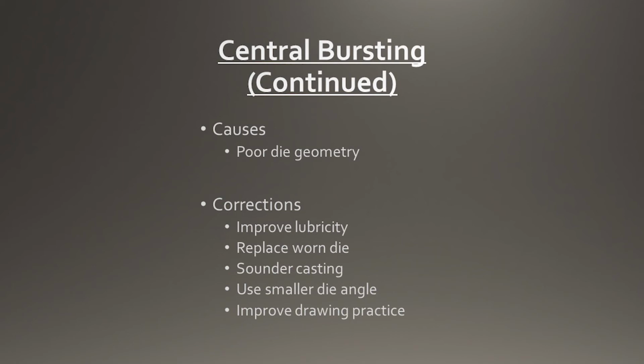Sounder casting, that's interesting. That means a defect in the cast bar or in the rod could exacerbate this particular problem. Smaller die angle, well, that's what I said. If you have too large a die angle, you have stresses inside the wire, and it can cause a crack, or improve the drawing practice. Well, let's see how all that comes together.